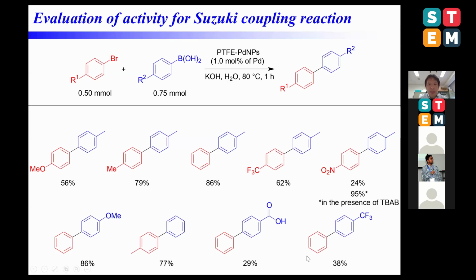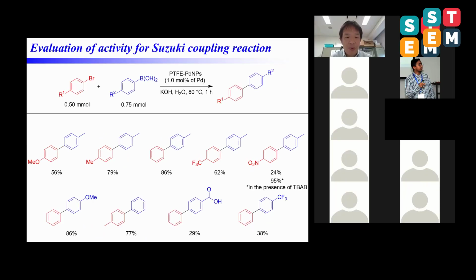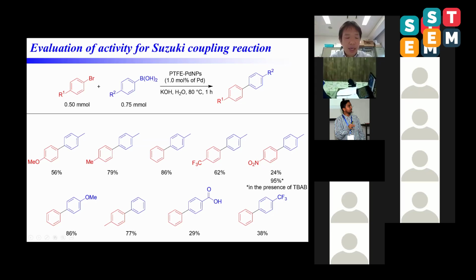The low yield in the case of 4-bromonitrobenzene would be caused by the reaction of 4-bromonitrobenzene with the catalyst being a solid-solid reaction because of the high melting point of 4-bromonitrobenzene. Indeed, the coupling product was obtained in 95% yield when performing the reaction in the presence of TBAB.